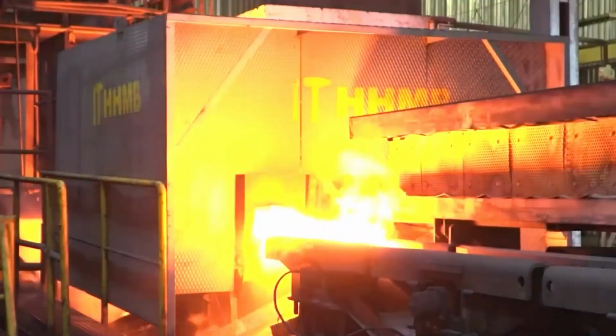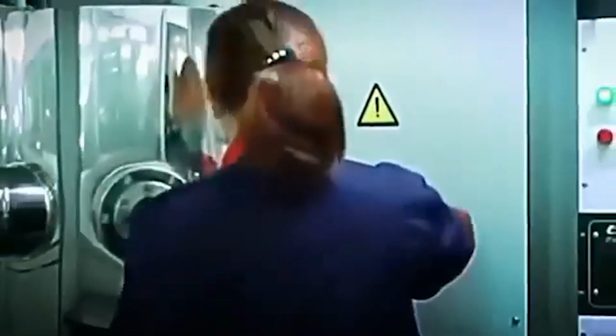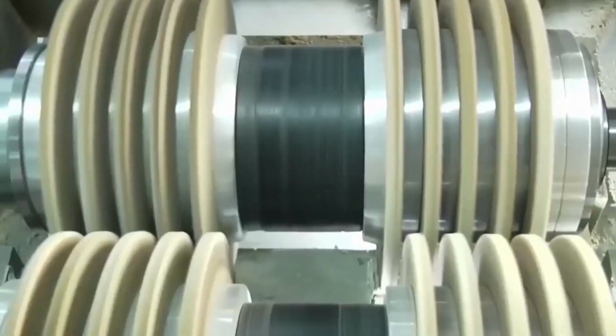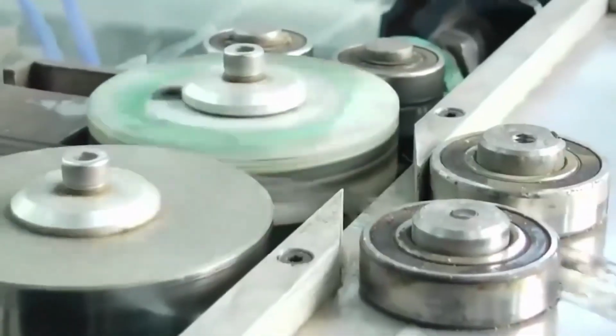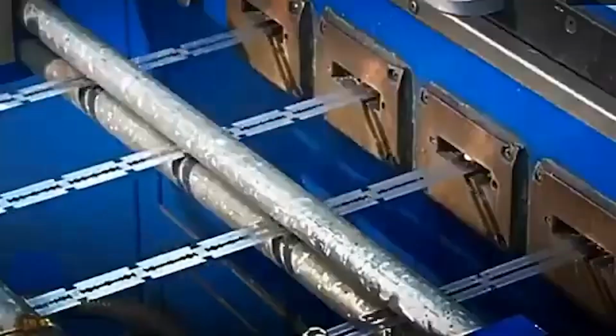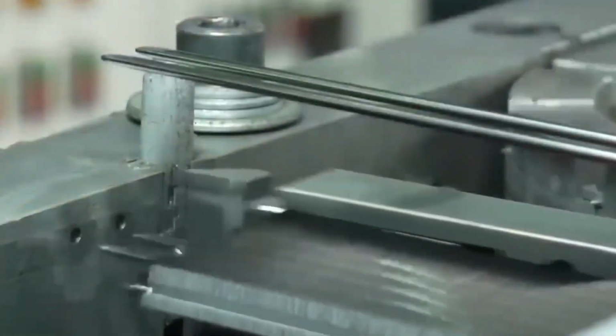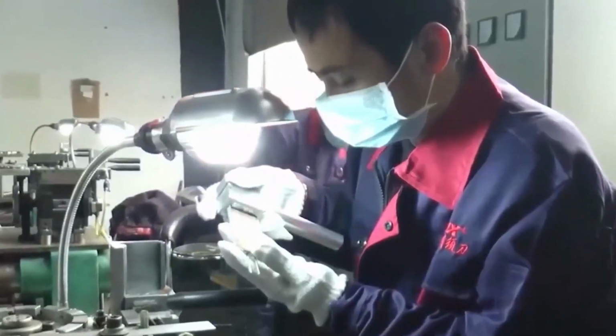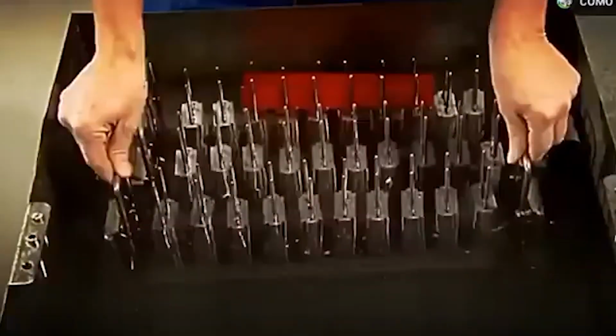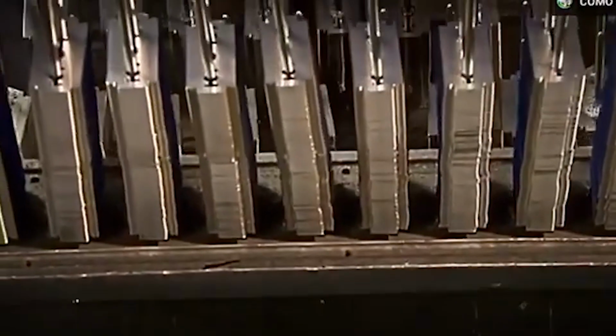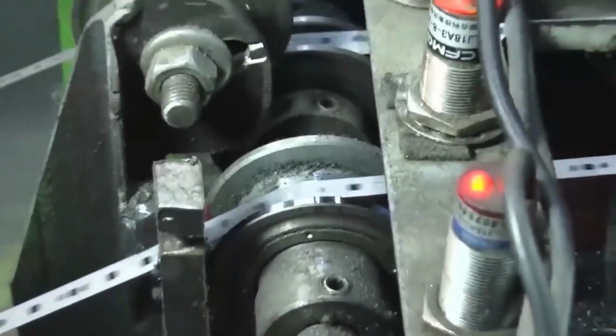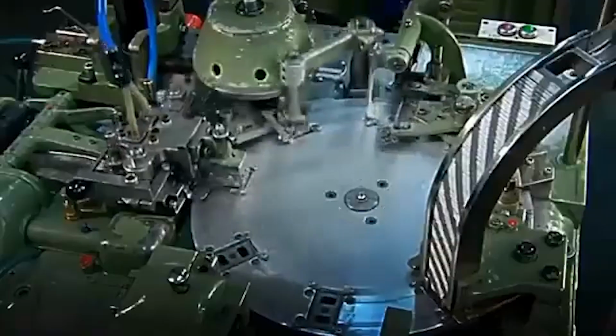them functional cutting tools. The hardened and tempered blade blanks entered the grinding department, where large precision grinding wheels, dressed to maintain consistent profiles, worked both cutting edges of each blade simultaneously. Material was removed at controlled rates to produce the double bevel geometry that defined the safety razor blade's cutting action. Edge angle consistency was critical. Variations of even 1 degree across the grinding wheel's working surface produced edges that felt noticeably different during use, being sharper on one section than another or harsher on one side than its opposite.